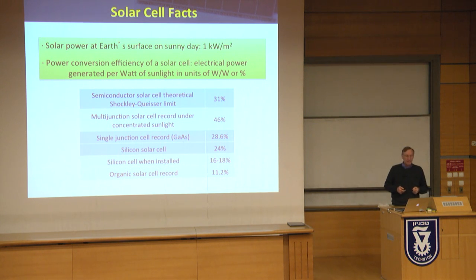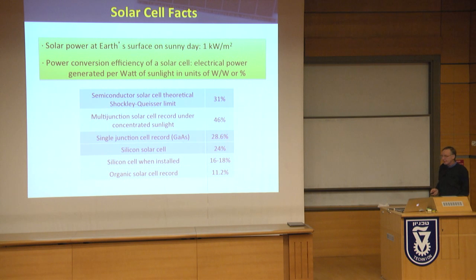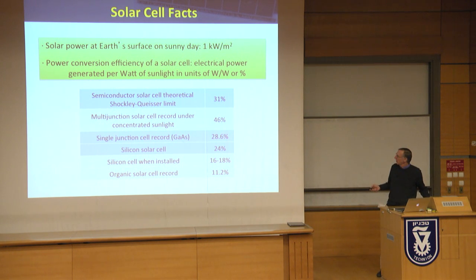This is where the world of solar cells exists today. The theoretical limit for a single junction cell is 31%. The highest efficiency that I'm aware of for multi-junction solar cells under concentrated sunlight is 46%, but that's a multi-junction cell, so it can break the limit there. The record single junction solar cell is 28.6%. That was announced by Alta Devices not long ago. Silicon solar cells are in the laboratory about 24%, but when you put them out in the field, they're somewhere between 16 and 18% for good silicon solar cells.